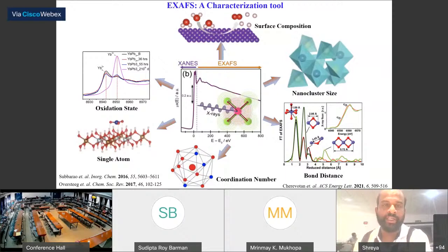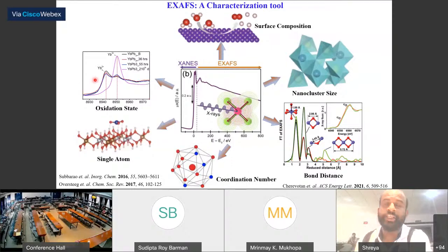EXAFS, as you know, is a very powerful technique. It can be used for understanding various parts of the materials design strategies. It can be used for understanding the oxidation state and how the charge transfer is happening, and to propose whether it's a single atom or a metallic system. We can also understand the coordination environment, and whether any deficiency can be tuned, by probing the local structure, whether it is forming a nanocluster,